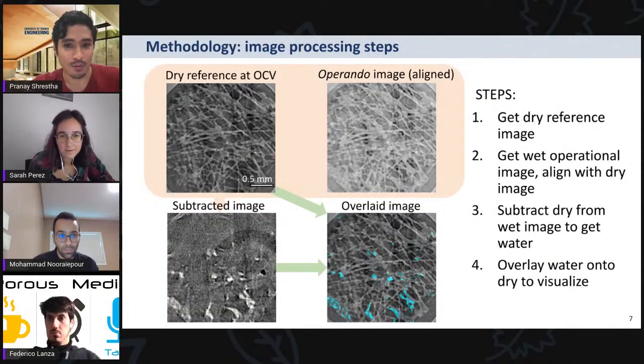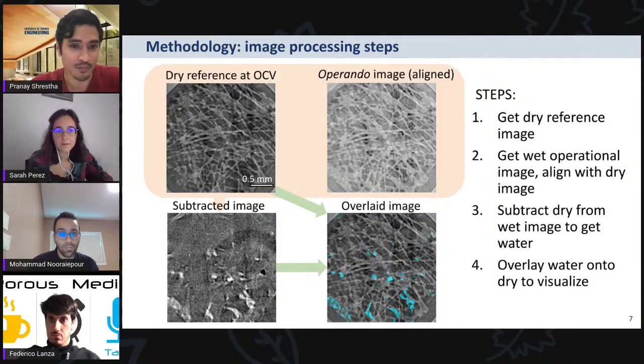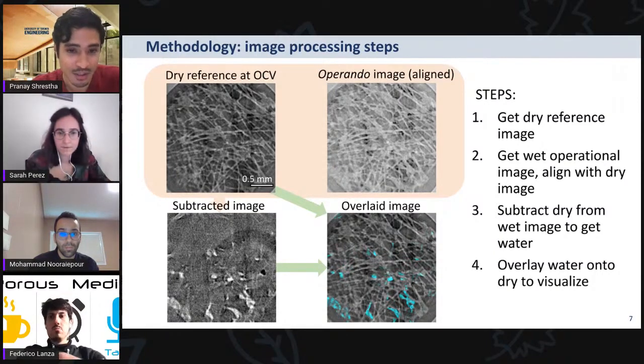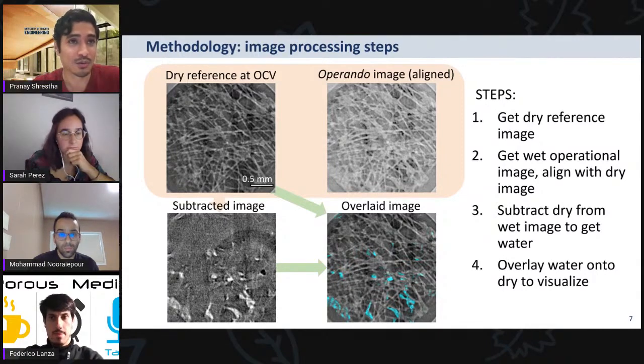So once we obtain the 3D image, we actually perform a subtraction, where the contrast between our carbon fibers and water is not very high. To account for that, we take a dry image where the cell is not operating, so we don't have any water produced, and an operando image where, with water production, the pores start filling up with water.